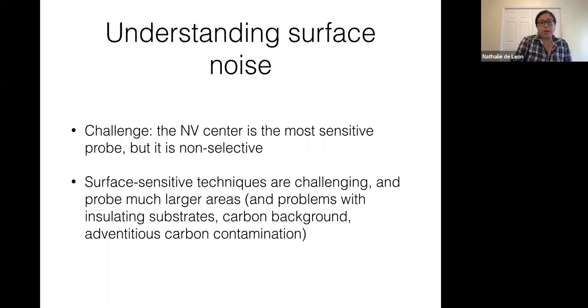So what we embarked on was a general project of trying to understand what was going on at the surface in detail. And one of the big challenges here is that the NV center is your most sensitive probe, but it's completely non-selective. All that it tells you is, I'm seeing a noise bath, and that makes me unhappy. But it can't tell you anything about what's causing that noise bath, and it gives you very limited information other than the spectrum of the noise.